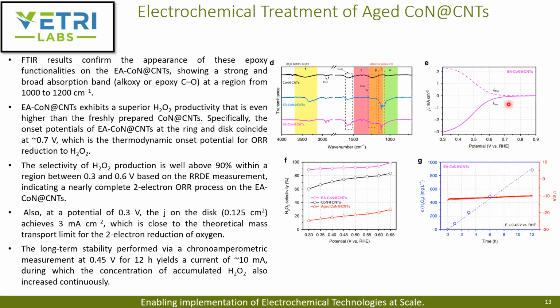And the overpotential was almost zero. It starts at about 0.7 volts. I mentioned earlier that they did this electrochemical production using a two-compartment cell. They measured the long-term stability using a chronoamperometric measurement at 0.45 volts for 12 hours, yielding a current of about 10 milliamperes. Then they measured the concentration of the accumulated peroxide using the permanganate titration method.